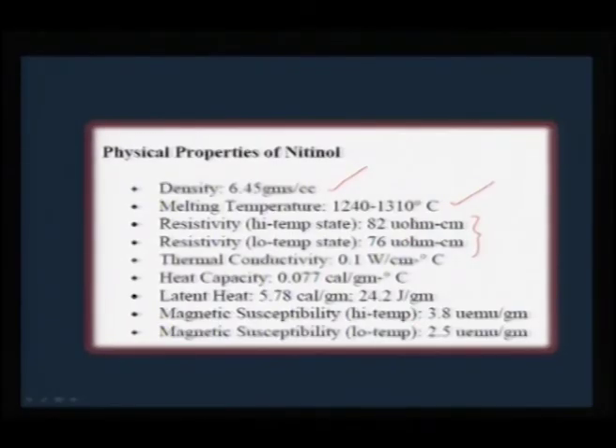For joule heating, for example, I will show some examples of how these shape memory alloys can be used to regain their shape using temperature. So, for joule heating, if you have resistivity along the same region at different temperature regimes, then it becomes very advantageous. Heat capacity is 0.077 cals per gram, and then magnetic susceptibility, although it is low, is quite comparable again at high temperature and low temperature. They show magnetic property of the order of micro emu per gram.